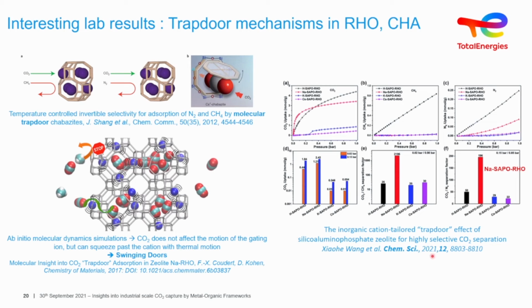And this has sparked much other work, and I very much like this publication, which is from this year. And we can see here that there's the sodium SAPO rho zeolite, so this time a rho zeolite and not the chabazite. And we can see that the sodium zeolite gives this nice separation factor here. Yeah, so very much of interest.